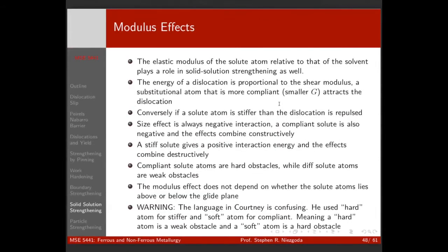Okay. So we also have, I mentioned on Wednesday, we also have a modulus effect, right? And remember the energy of a dislocation is G b squared, right? So if your dislocation gets near an atom where the bond stiffness between the solute and the matrix is different than the matrix, you're going to affect the energy of the dislocation in that region because your bond stiffness is different, right? So we saw size effect is always a negative interaction. If we have a compliant solute, that's also going to be a negative interaction. But if we have a stiffer bond, that gives us a positive energy, right?